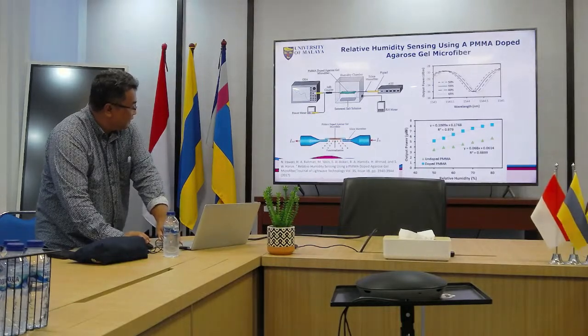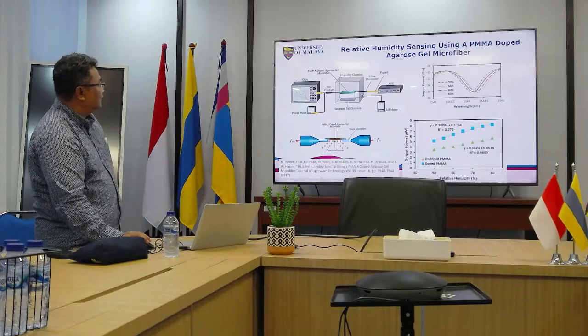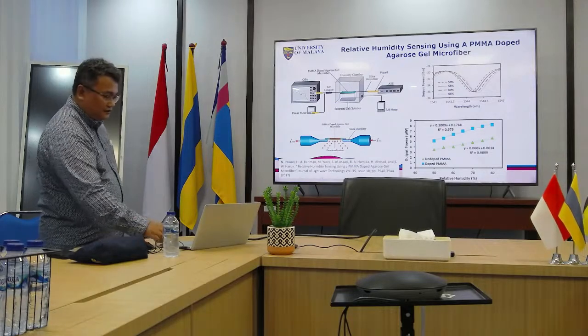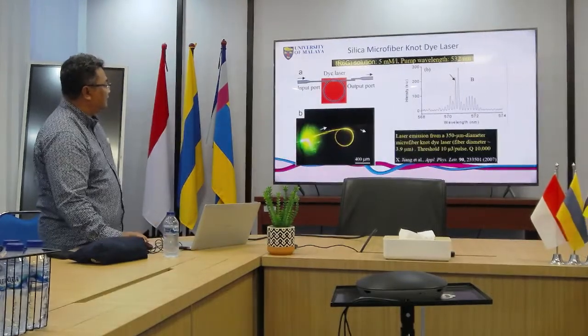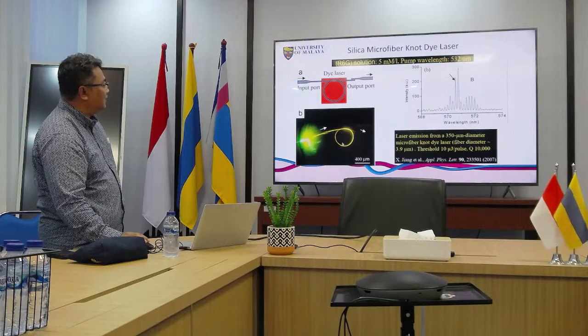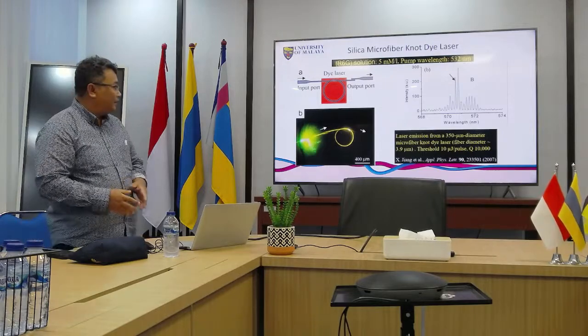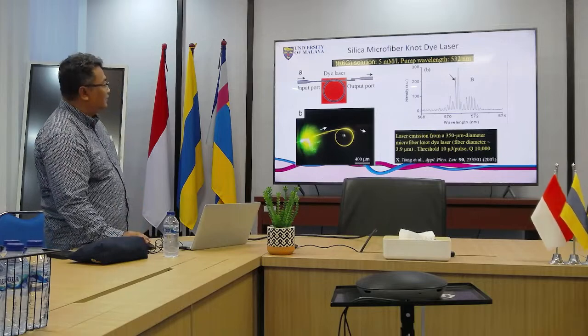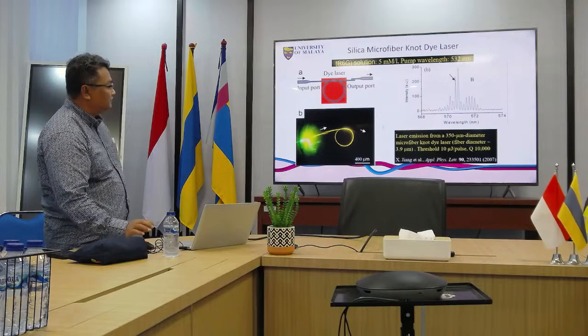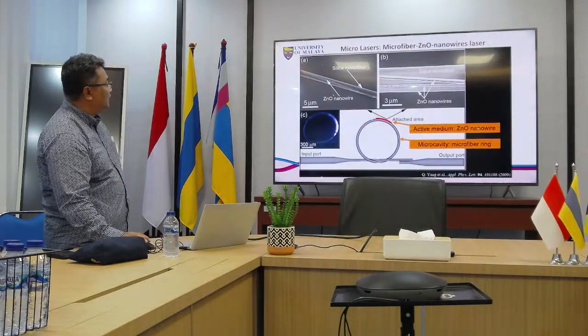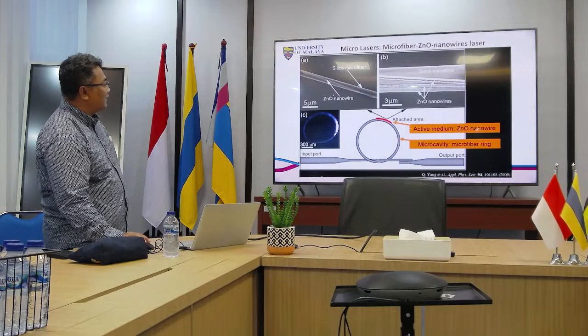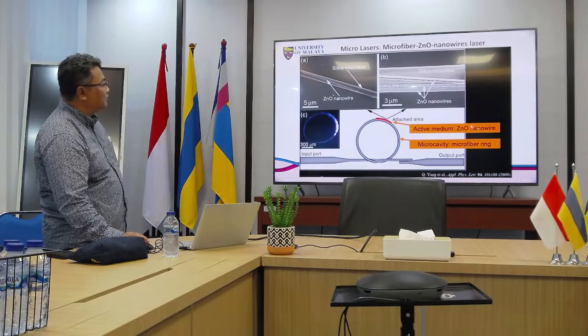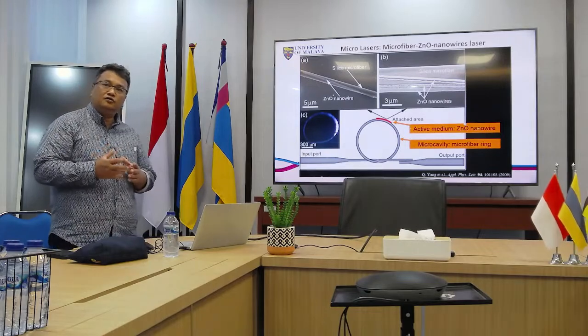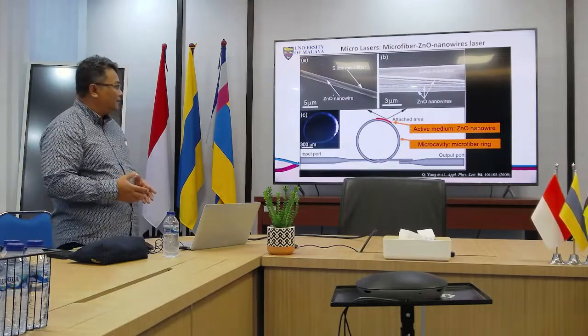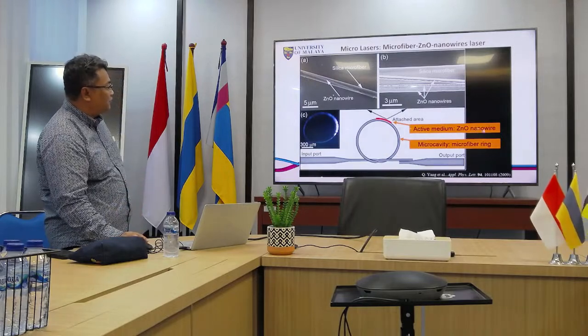And this one we do with agarose. You put agarose for humidity sensing. We put the dye, you can make small lasers, 400 micron lasers. You put this zinc oxide nanowire, you attach it to this structure, so we can generate UV light, because zinc oxide can be used to generate UV light. People have demonstrated this for UV laser.